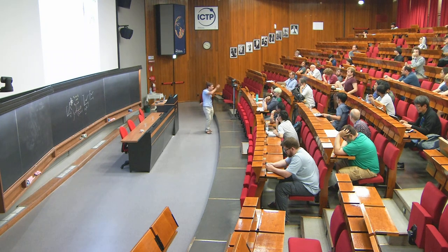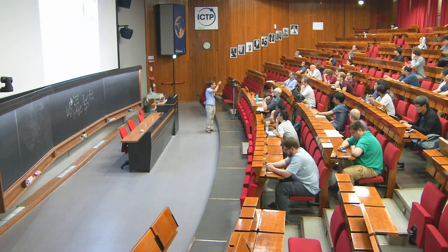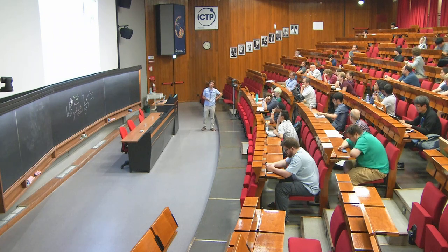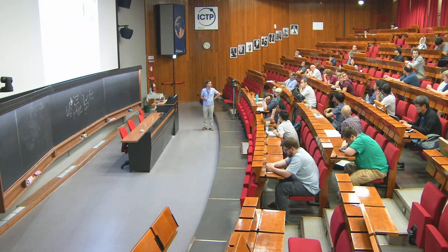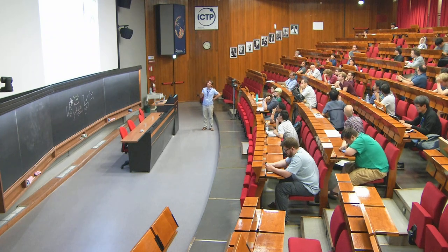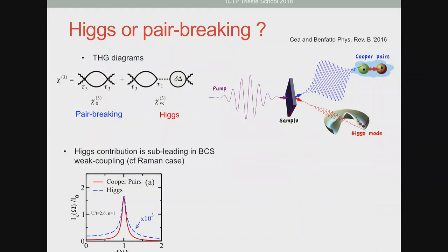It's kind of a borderline case. It's really at the border of the continuum. Okay. So if you do that, you realize that generically this contribution is actually several orders of magnitude smaller than the pair breaking contribution. So this is essentially the intensity as a function of omega.